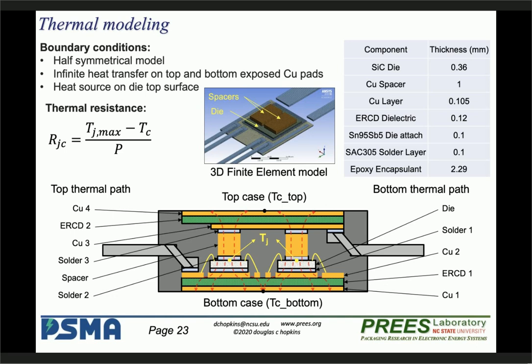Layer thicknesses is one of dielectrics. Also, positioning of different dielectric materials within the structure to do field warping, to be able to optimize the voltage profiles on the highly stressed dielectric areas. For instance, if you're going to use a silicone gel, you want to make sure that your dielectric stress at high field intensity points is being managed so that you don't have localized breakdown and degradation over time of your encapsulates.